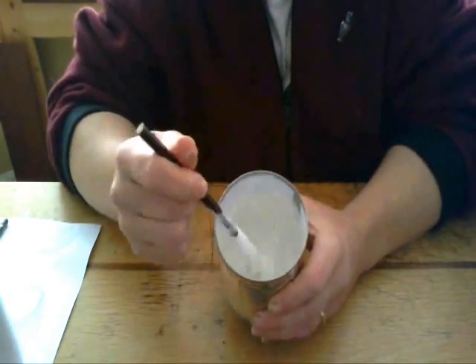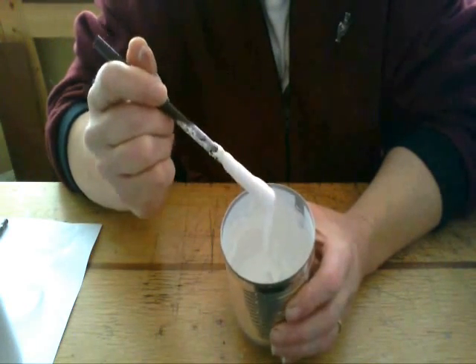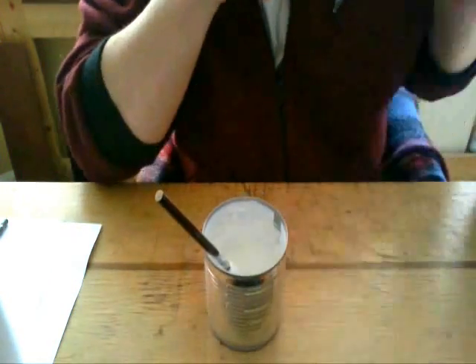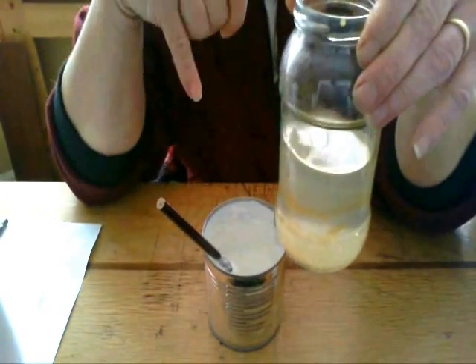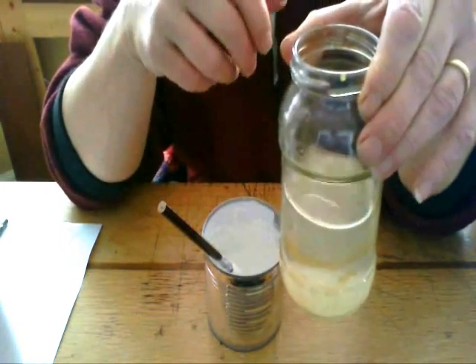So there is my mix of PVA, water, glycerol, and talcum powder, and it's a reasonably stiff paste. Now what I've got here is a 4% solution of borax. The minute I add that, it's going to start cross-linking and it'll bind it up and become fairly thick.